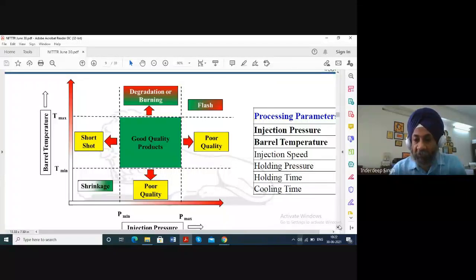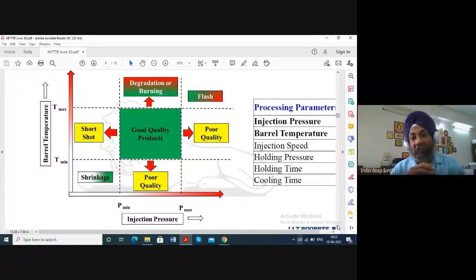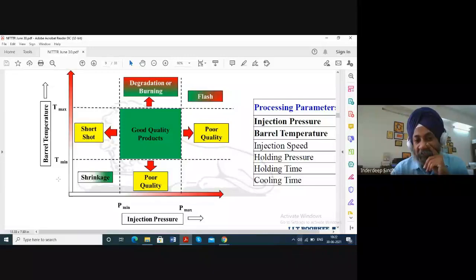So, injection pressure. You see here that for good quality products, there is an optimal window in which we should select our injection pressure and the barrel temperature. If the barrel temperature is too low, there are defects. If the barrel temperature is too high, still there are defects.